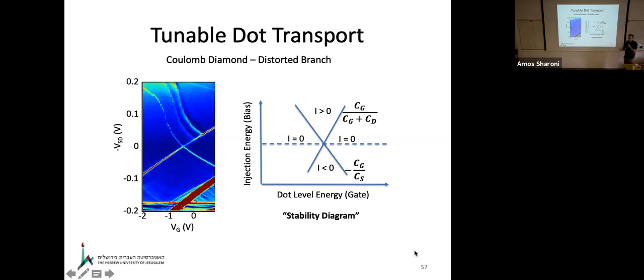This is graphene, hBN, graphite, no superconductor. There are actually few defects, but I'm showing only one. So if I tune the gate, I see this cross is from a single dot. These are excited states at about 50 and 70 millivolts. So these are excited states of the dot. There are other dots, but that's a single dot. And so that's measured at 4 K. So that's a relatively elevated temperature. And the slopes here are actually a measure of the capacitance, it's actually a measure of the density of states of graphene. And that's something which took a lot of work to prove.